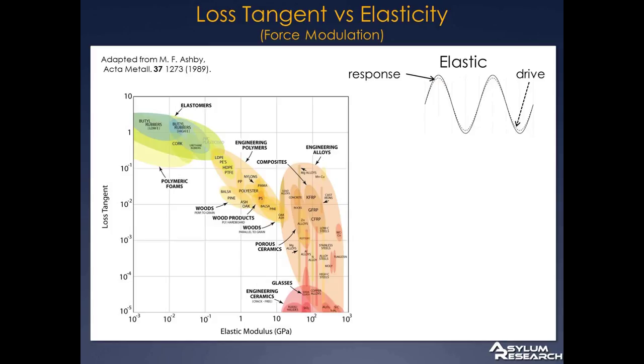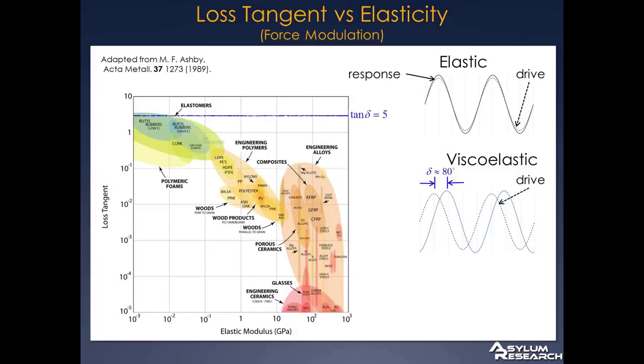Many materials, so this is what all this stuff down here with really low loss tangents would look like, metals and so on. If we take some polymers or rubbers and we drive those, what we'll see is that the response has a phase shift. It's out of phase. It lags behind. And those materials we call viscoelastic. Now this phase angle, the angle between the drive and the response, depends on the loss tangent. We can take that phase angle of 80 degrees here, plot that tangent, and we see that that's the sort of loss tangent you'd expect for one of these very lossy butyl rubbers or some other elastomer.